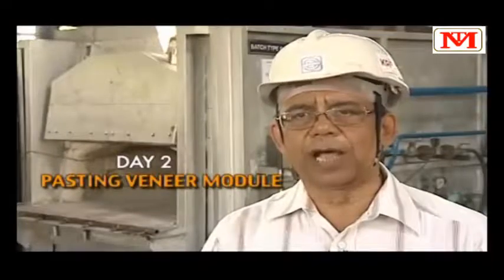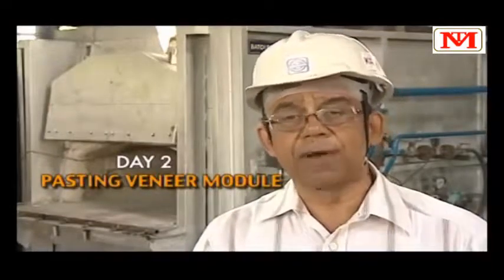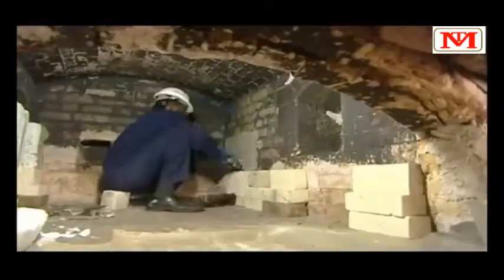Day 2, the veneering module will be kept above the refractory surface, applying the mortar, which will stick on the refractory as a hot base insulation. For that, 24-hour drying time will be required.